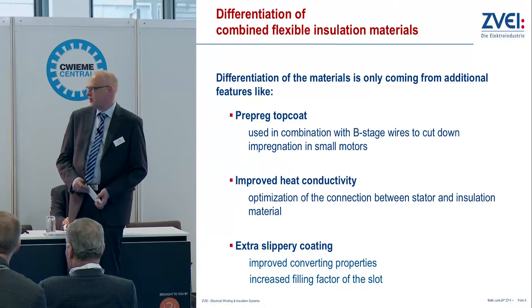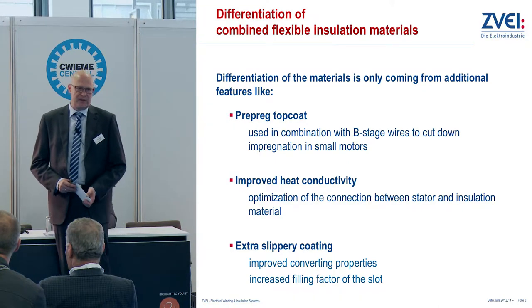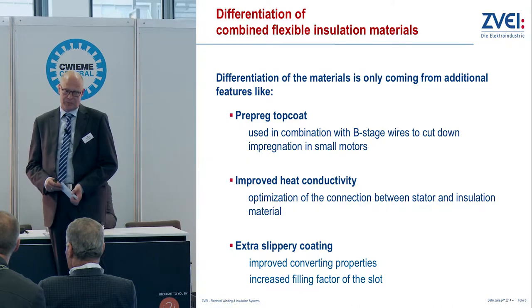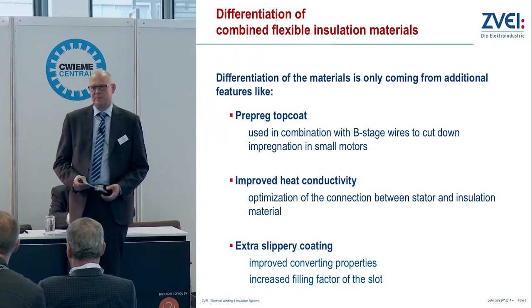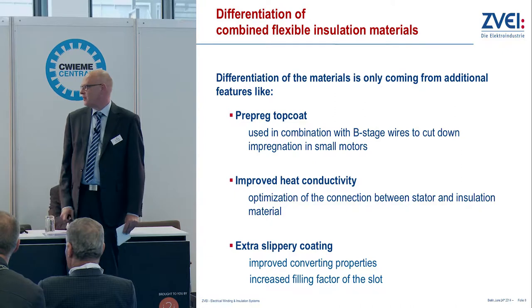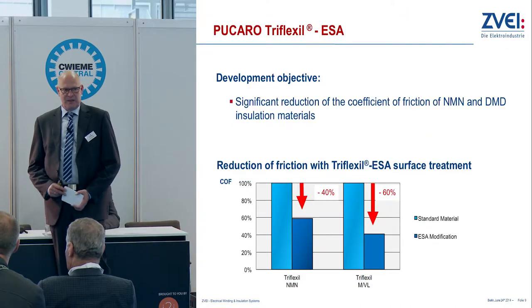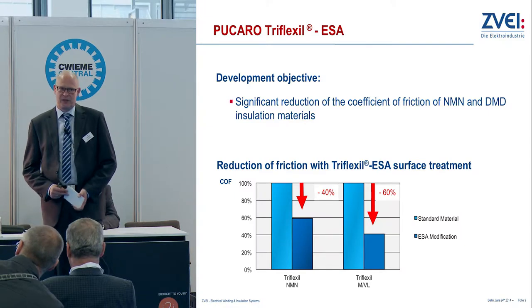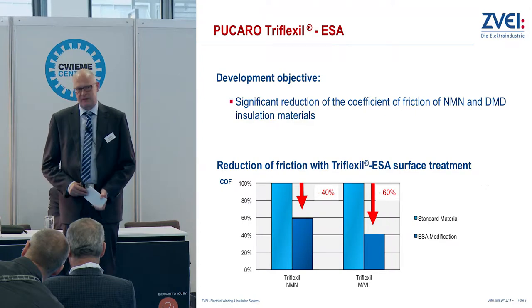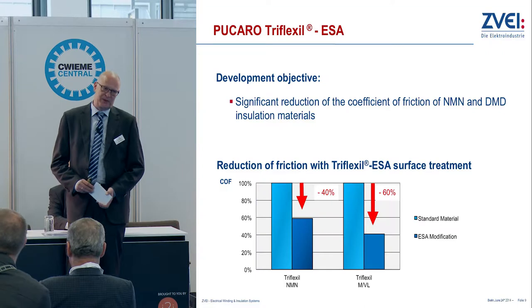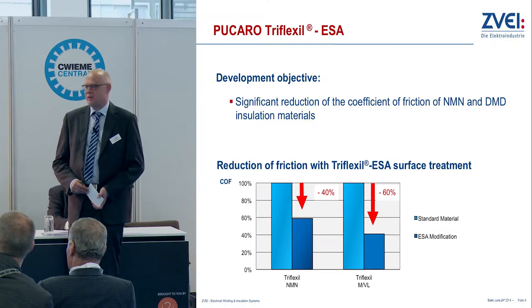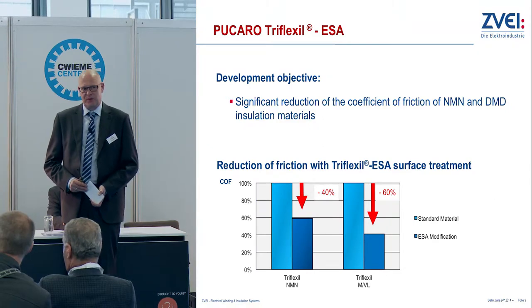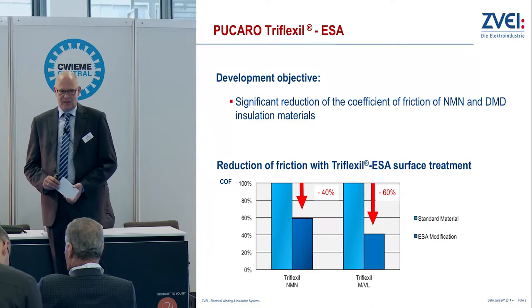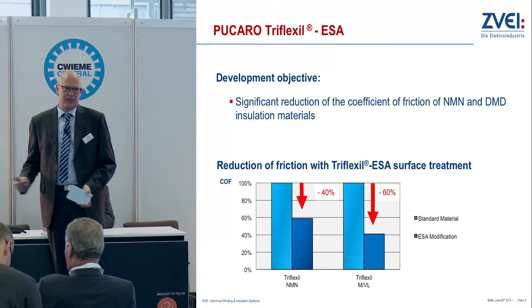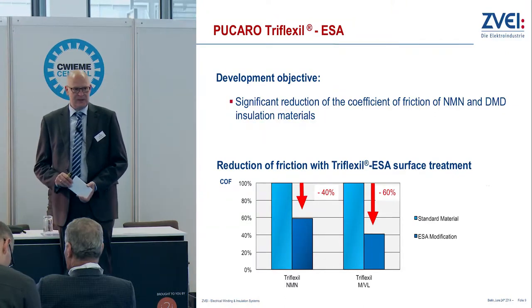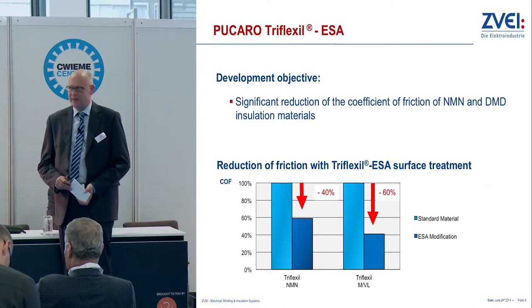And the main issue I'm talking about today is how to increase the filling factor and reduce the motor size while having the same output of the motor. In this case, we developed a new material in the last 2 years, and we achieved an improvement in the coefficient of friction of our insulating material of 40% for NMN grades and 50% up to 60% for DMD grades. This will result in a higher speed of automatic inserting machines, and this will allow you to increase the filling factor in the automatic inserting machines. As you all know, the filling factor in automatic winding is lower than in hand winding. So we want to achieve a similar filling factor also for automatic winding machines.